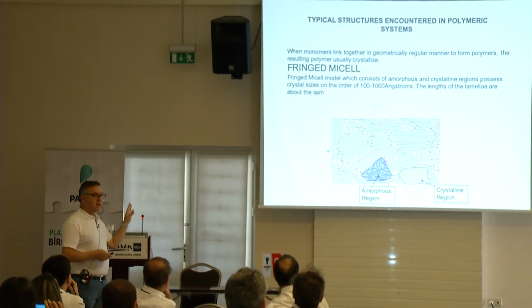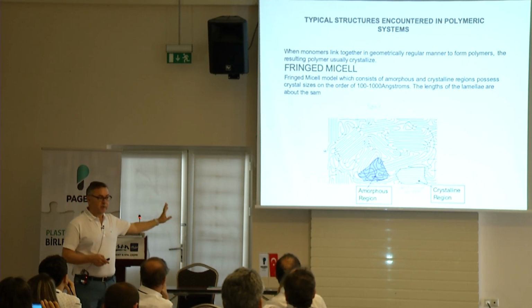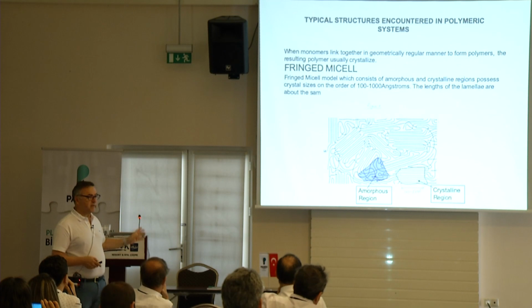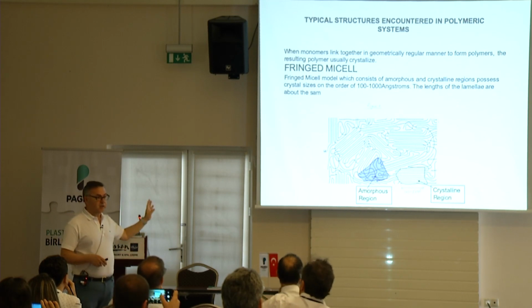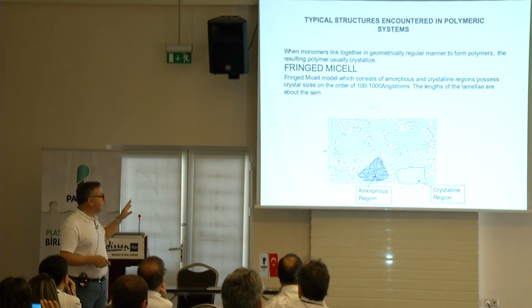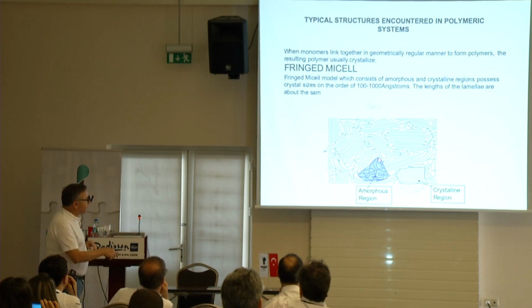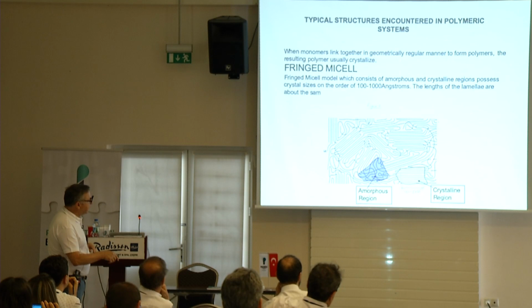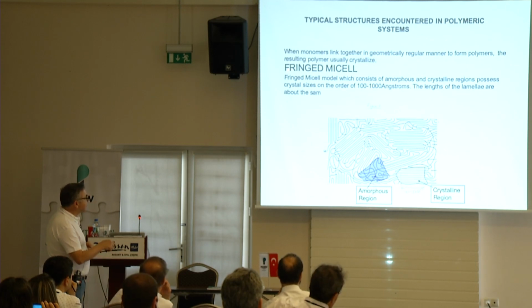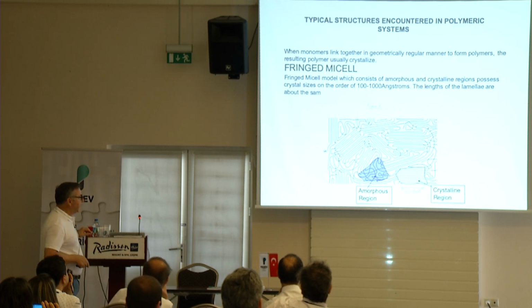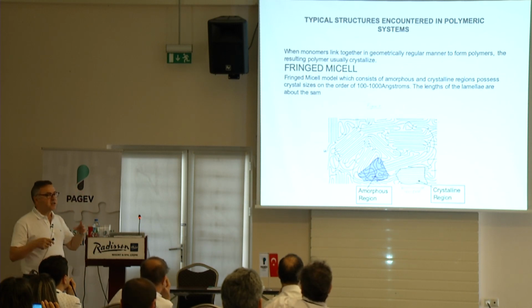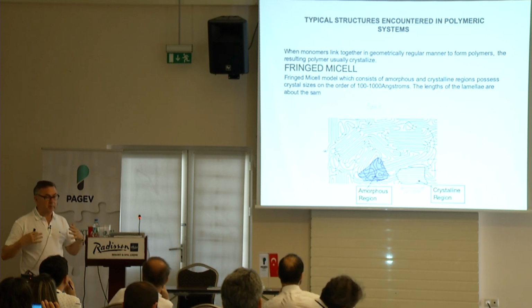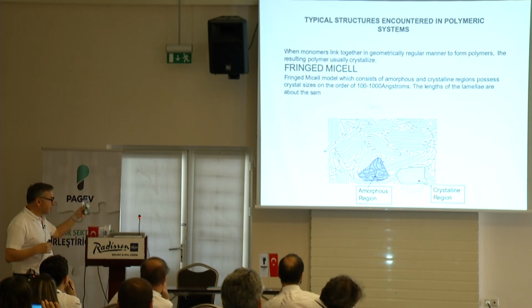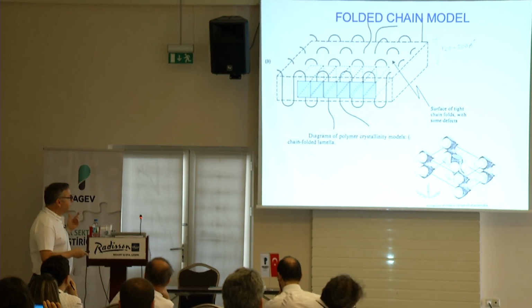When they crystallize, there was a lot of controversy. Let me give you a little history of morphology of polymers. Up until the 1950s, they weren't sure exactly how the crystals formed. Many people thought that these sort of structures exist, and then nothing else matters. So there are amorphous regions, and there are crystalline regions, and in between there are some disordered regions. They call this the fringed micelle model. It turns out not to apply to everything, but it applies to some relatively semi-rigid materials like polyesters, materials that have difficulty folding.